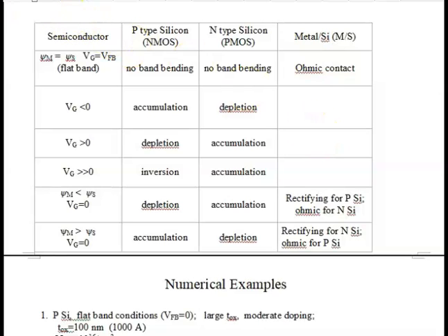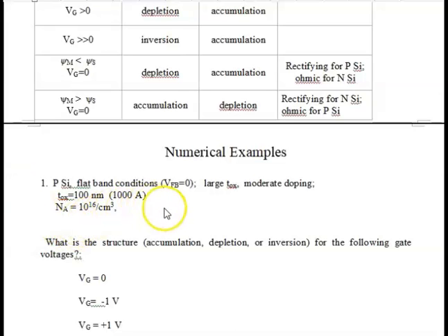Now we're going to look at some numerical examples, and we're going to start with the flat band voltage equal to 0. The work function difference is 0, and we're going to start with a large oxide thickness and moderate doping. Moderate doping would be 10 to the 16th. Notice it's acceptor doping, which is consistent with p silicon. More normal doping today would be about 10 to the 17th, but this is the real issue here. We're starting with 1,000 angstroms of gate oxide.